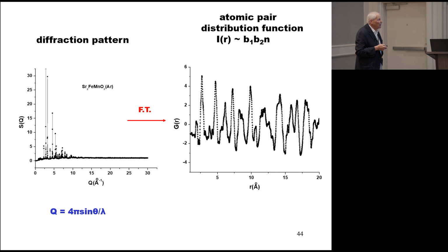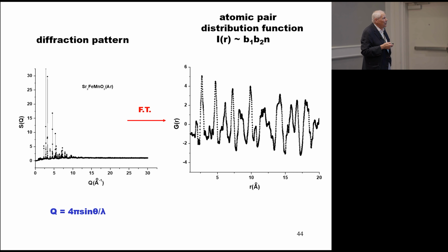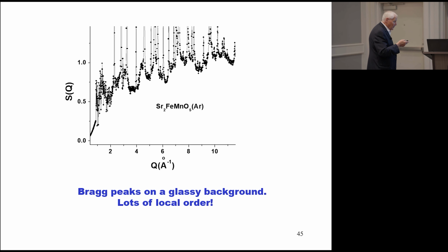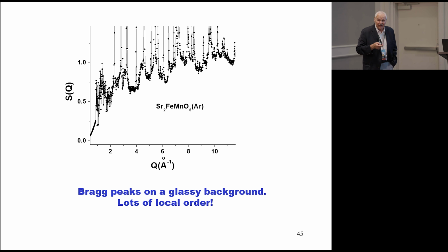Each peak in the G of R, the intensity of each peak is proportional to the product of the scattering lengths of the two elements involved in the pair and the number of pairs that you've got at that distance. Okay, just to show how this works, what we mean by total scattering, you get information both on the average structure in these very sharp peaks, and then a huge amount of information in the background.